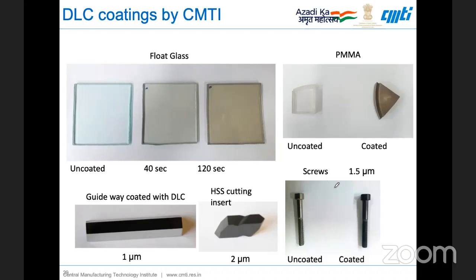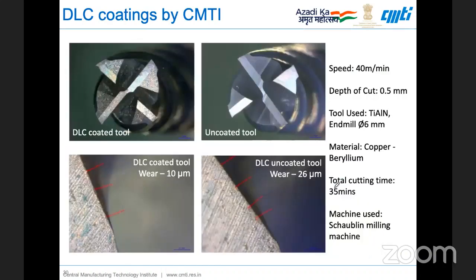Then even for cutting tools, you can use this. Just to show the difference you can notice, an uncoated cutting tool has a wear of 26 micrometers after about 35 minutes. For a DLC coated tool, the wear seen after 35 minutes is just about 10 micrometers. So we can say with confidence that DLC has absorbed most of the impact during the cutting, and hence it has subsided the wear of the cutting tool. Only after the coating has been removed can you actually notice wear on the tool. So this is also very good for cutting tools.